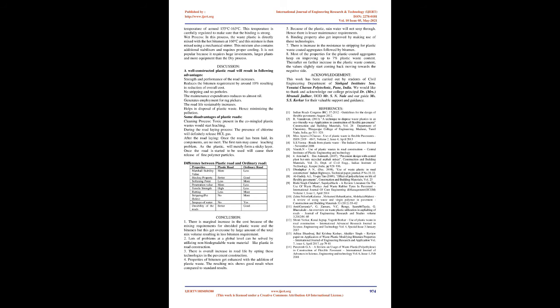Conclusion. 1. There is a marginal increase in the cost because of the mixing requirements for shredded plastic waste and the bitumen, but this gets overcome by the large amount of the total mix volume, resulting in less bitumen requirement. 2. Lots of problems at a global level can be solved by utilizing non-biodegradable waste material like plastic in road construction. 3. There is an overall increase in road life by opting for these technologies in the pavement construction. 4. Properties of bitumen get enhanced with the addition of plastic waste. The resulting mix shows good results when compared to standard results.